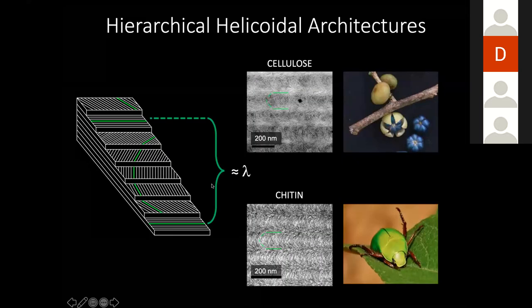And interestingly, in nature you find, both in plants and in the animal world, polysaccharides that come in fibrils, like cellulose and chitin, that can be arranged into this helicoidal structure and produce coloration. So the blue of these berries that you can see in this first picture is not coming from any pigmentation. It comes from cellulose organized into this helicoidal architecture. And the green of this beetle is the same; it comes from a helicoidal architecture made of chitin.